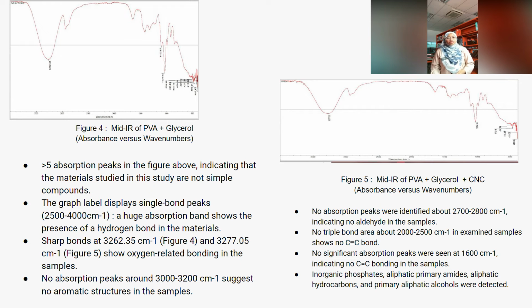Oxygen-related bonding in the samples is demonstrated by the presence of sharp bands at 3262.35 in figure 4 and 3277.05 in figure 5. Because the samples that were tested did not exhibit any additional absorption peaks near the wavelengths of 3000 to 3200, it can be deduced that they did not contain any aromatic chemicals. In addition to that, there were no more absorption peaks around the wavelengths of 2700 to 2800. This could be the evidence that the aldehyde was not present in the samples that were analyzed.